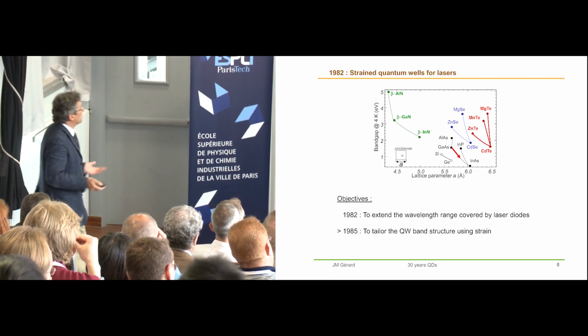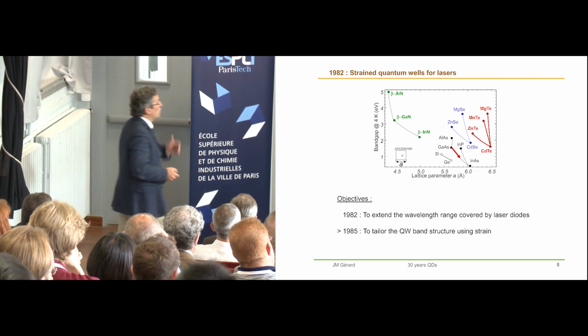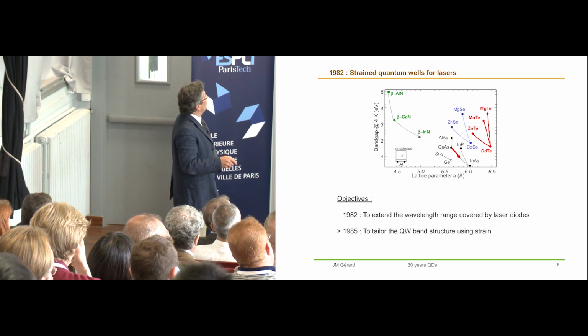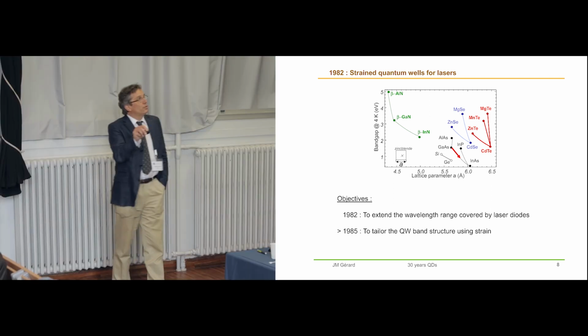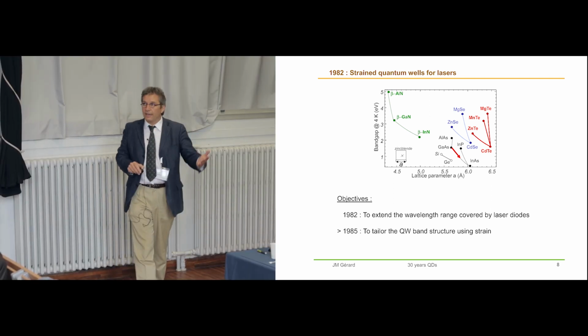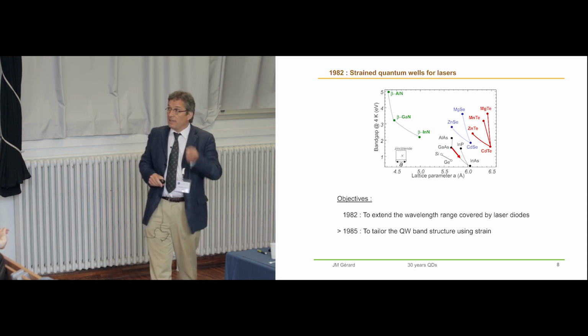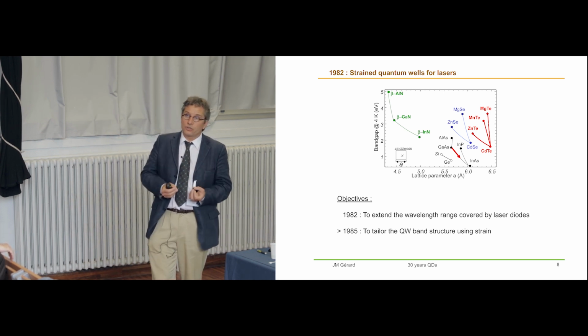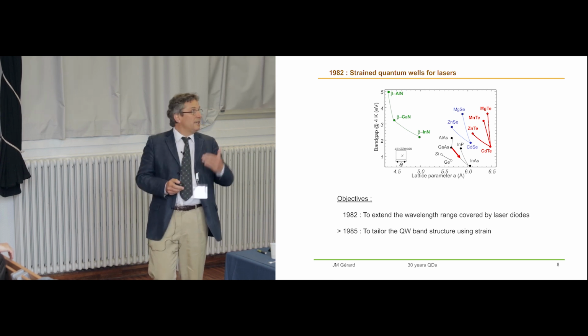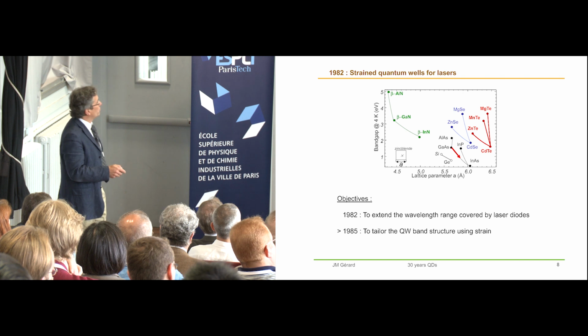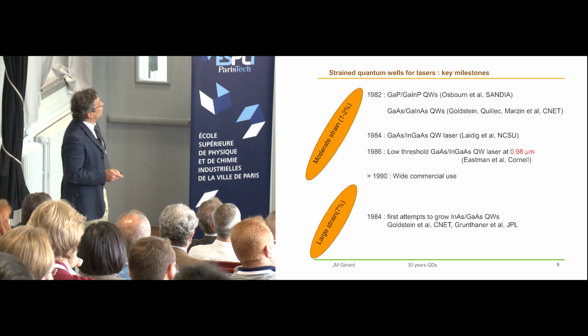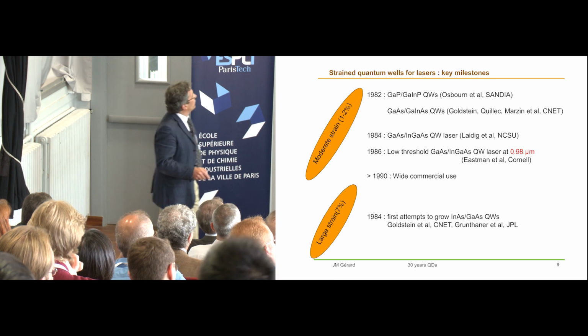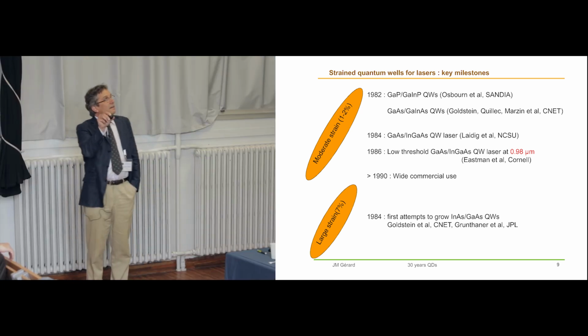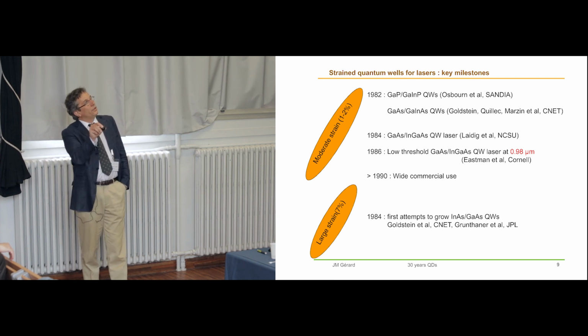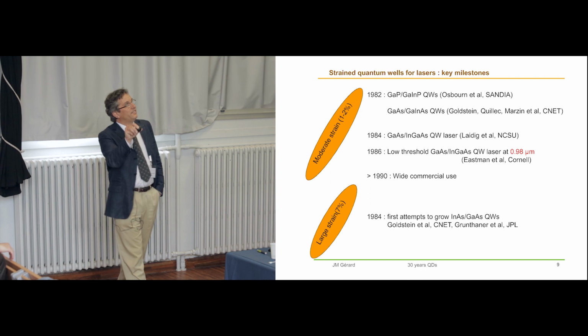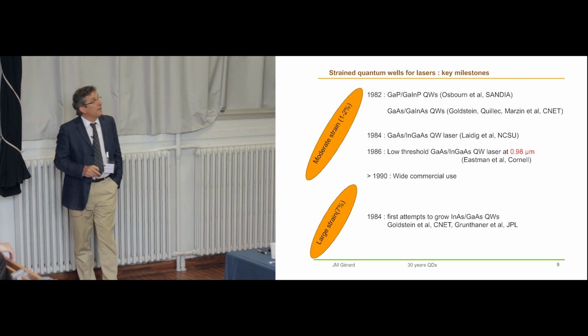So it works. It's perfectly possible to grow strained quantum wells with a good quality. And so in 82, the goal was really to extend the wavelength range covered by lasers. But after that, people realized that by putting strain, you also tailor the band structure of the quantum well. And so you can also improve the quantum well properties like that and the laser properties like that. So two labs have played an important role at that time. Sandia, with Osborne, Gourley, and co-workers, and France Telecom Labs, CNET, with Goldstein, Quillec, and Marzin.